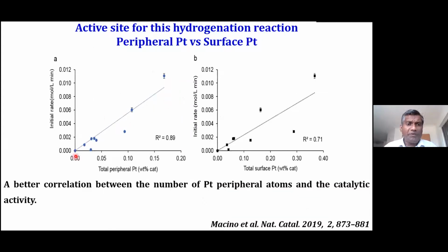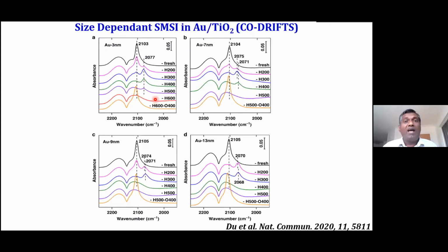And what we did, we tried to correlate peripheral sites with total surface platinum exposed sites. So we tried to correlate the reactivity or initial rate with the total exposed platinum surface. We didn't get a very acceptable correlation, whereas when we correlated the peripheral sites versus the rate of the reaction, we had a slightly better correlation. That shows that the peripheral sites, the platinum-titanium oxide peripheral sites, are responsible for the better activity of this reaction. And after that, a couple of groups started reporting this size-dependent SMSI in gold on titania, for example, Du et al. I think they are from Dalian Institute.